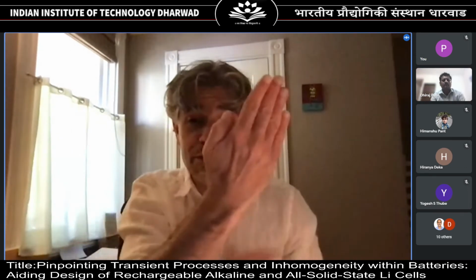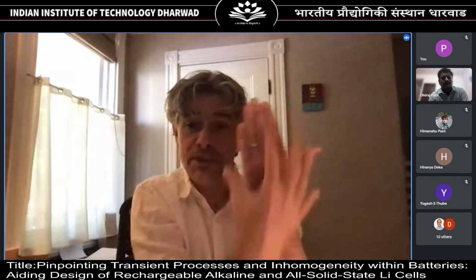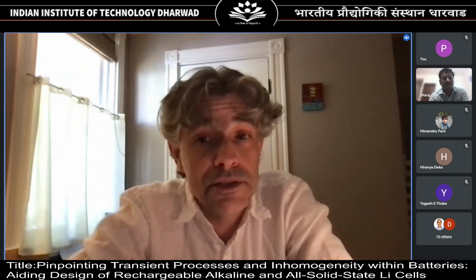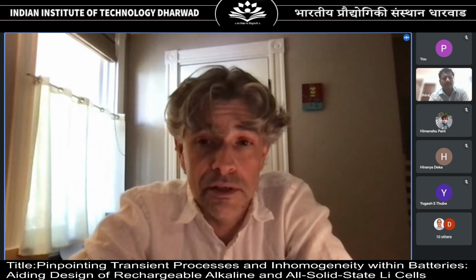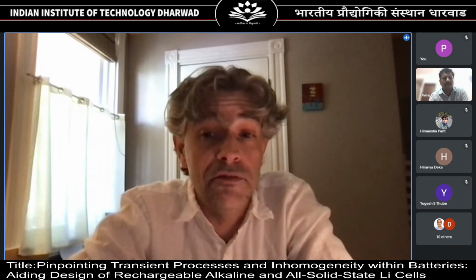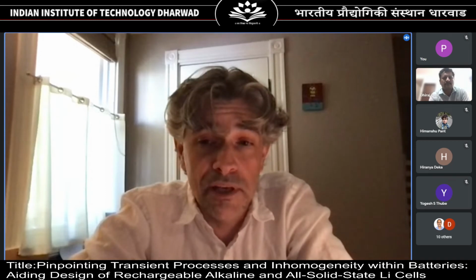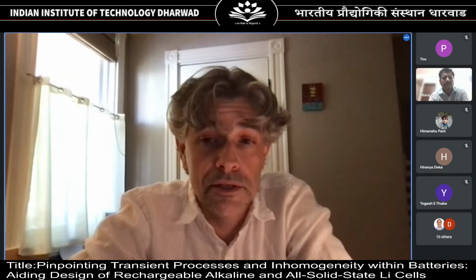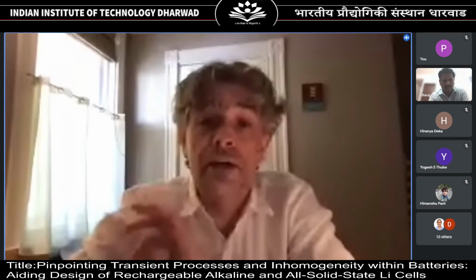And if you were to take one of the layers and look at it, you would see a pattern of vacancies on it. And that pattern of vacancies is also something that changes the identity of the material. So these materials can get very, very structurally complicated. And the more complicated they get, the harder it is to probe and find out exactly what they look like.